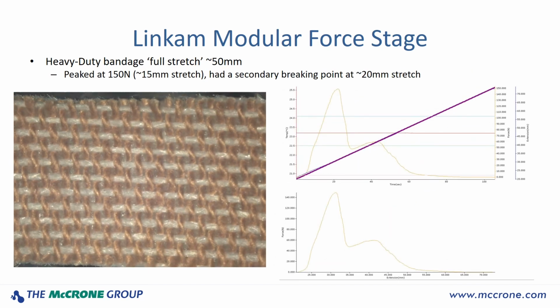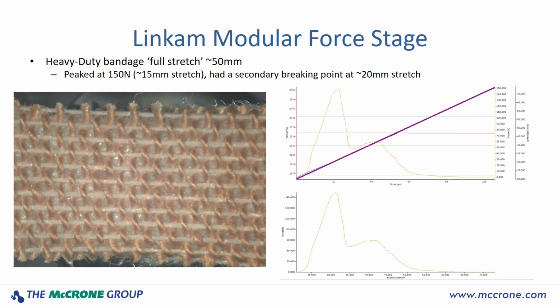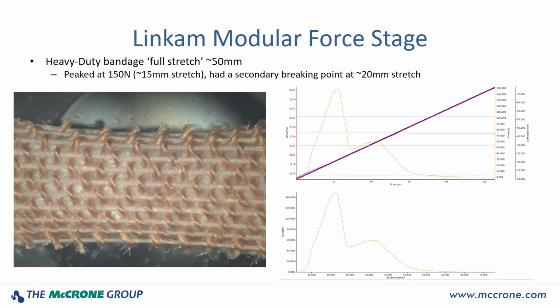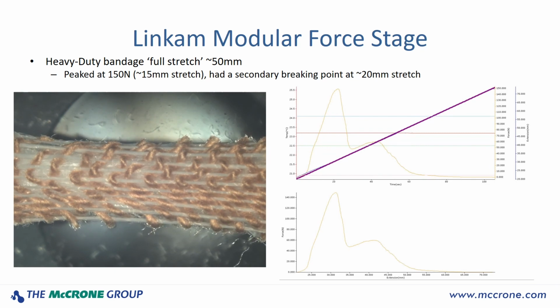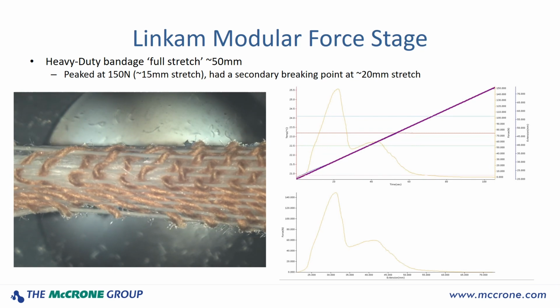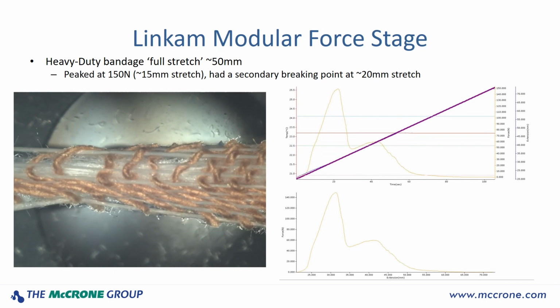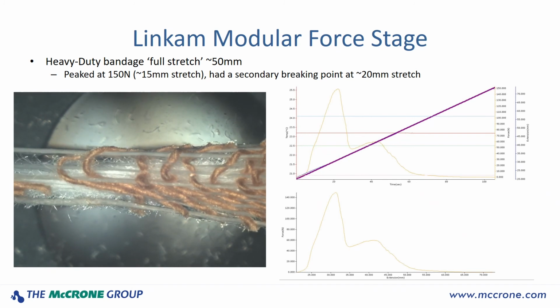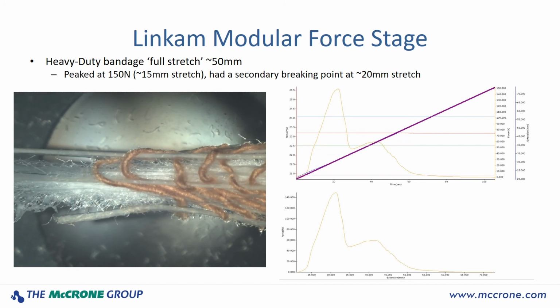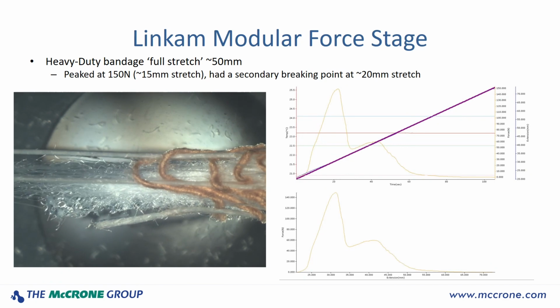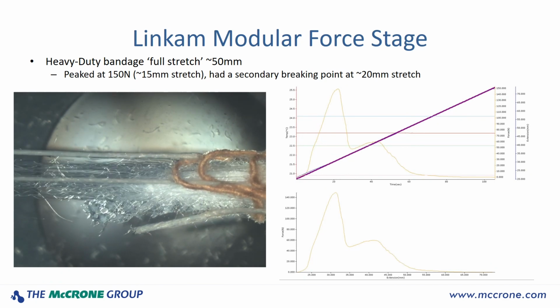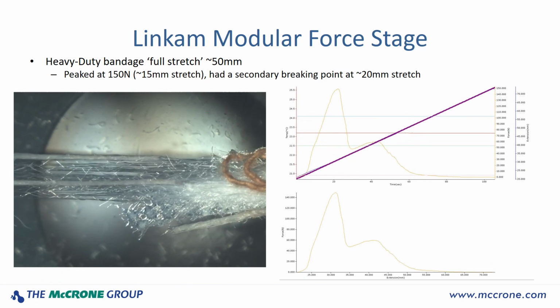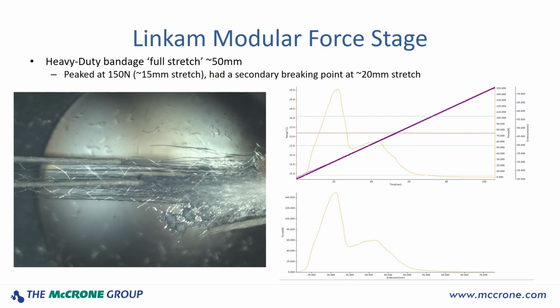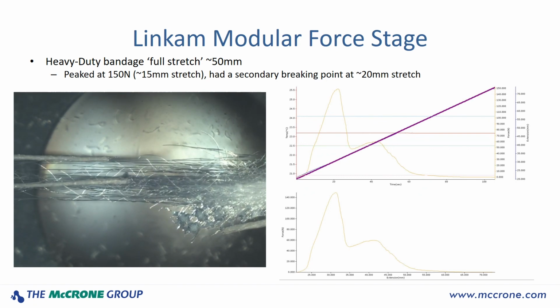The final test that we did for the heavy-duty bandage was another full stretch. We saw slightly different results for this bandage, as there was 150 newtons required to reach the initial breaking point, and then it seemed that there was a secondary breaking point around 60 newtons of force. This could have been from the woven material being tangled in itself after the initial tear, but overall we saw much more force required to reach that initial breaking point with this bandage.